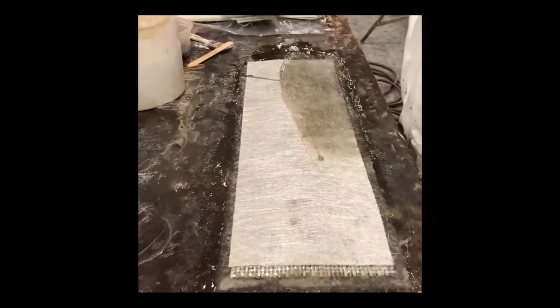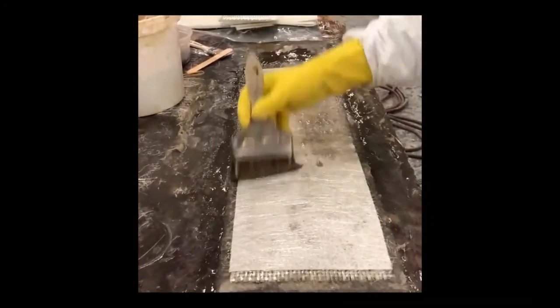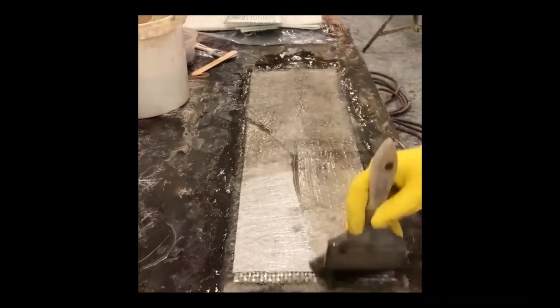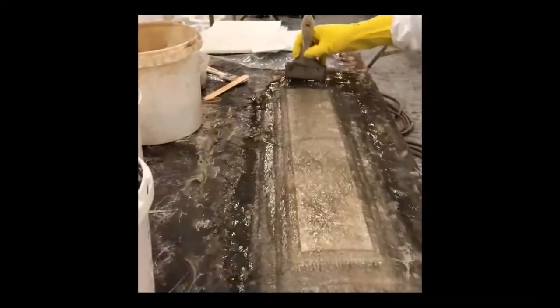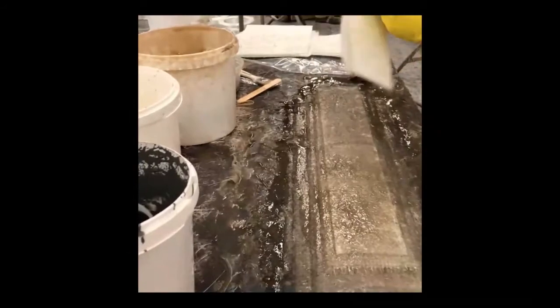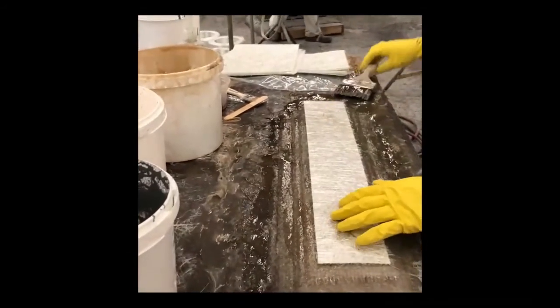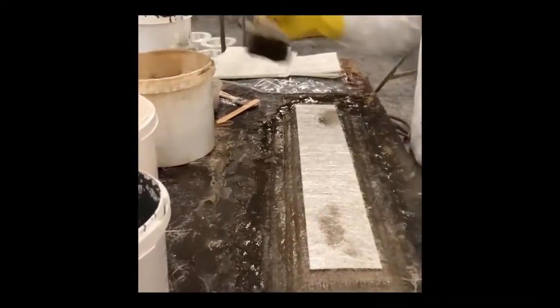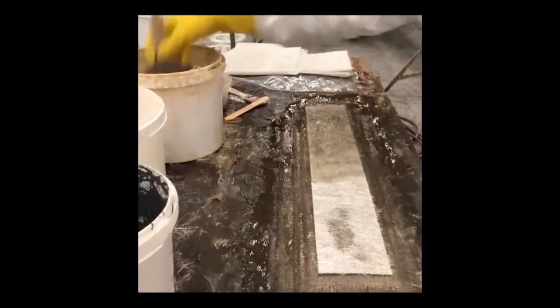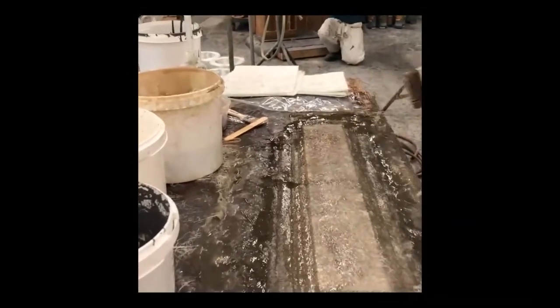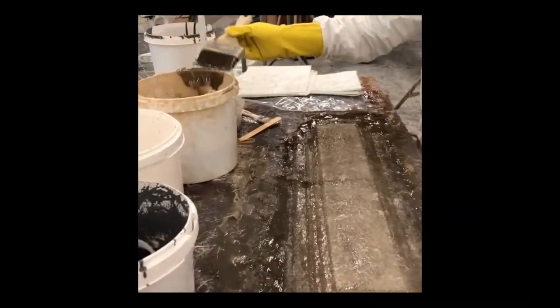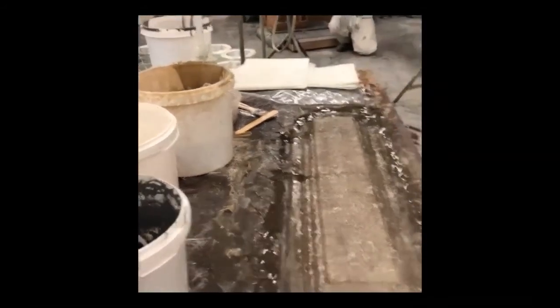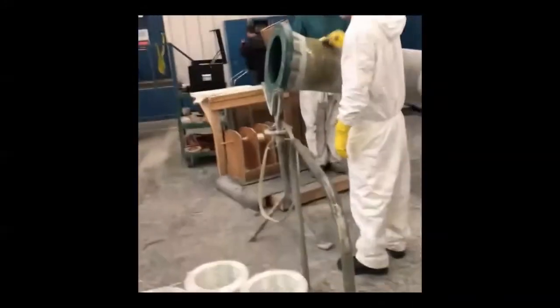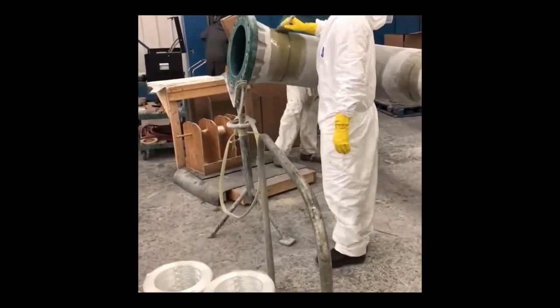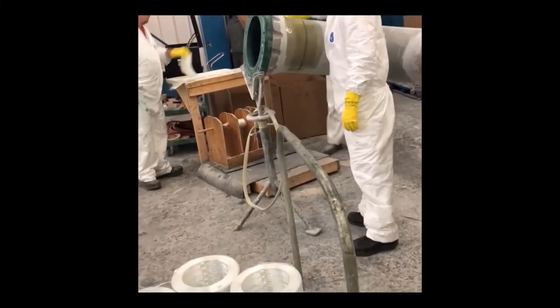One thing you're not seeing in the video, the technician can also roll out these layers with a roller, and you're going to see in a minute when he does that on the pipe, he could also do that right here on the surface. So he's going to put his last layer on here. He's going to saturate that with resin. And then he's going to take some of his catalyzed resin and put it on the pipe that's been fit and sanded. It would have been sanded within at least the last 4 hours or you'd resand it. So that pipe has been recently sanded. He takes and applies some of the catalyzed resin to it.